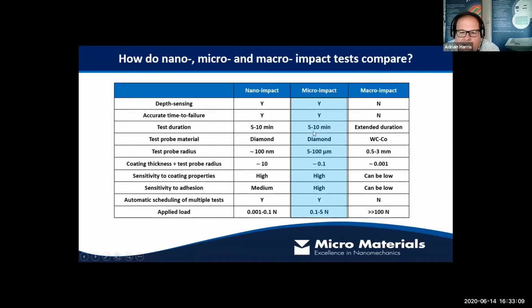We don't really get that with the macro scale tests. The tests are short, okay? So 5 to 10 minutes, 10 minutes at the absolute maximum, really. We tend to use a diamond probe. You can use other probes, but diamond probes are prevalent in this type of testing. And tips from the region of 100 nanometers radius up to about 100 microns maximum. A useful way to choose the right tip is to consider the ratio of the coating thickness to the test probe, and this kind of 0.1 ratio is about right.